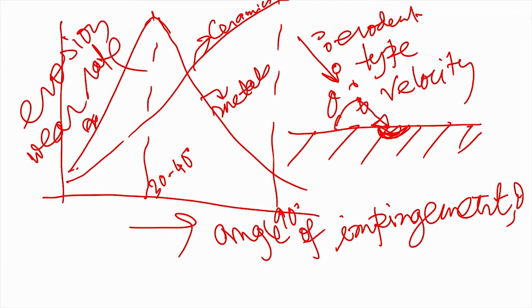So, the point that I am trying to make here is that when you do erosion wear experiments with metals, you should conduct these experiments preferably at 30 to 40 degree, because at 30 to 40 degree the erosion wear goes through a maximum. When you develop new materials for wear resistance applications, it is important and imperative to understand their wear mechanism and also measure their wear loss at the most aggressive wear conditions as much as possible. So, for ceramics, the angle of impingement should be 90 degree to assess the wear resistance under the most aggressive conditions, and that is an impingement angle of 30 to 40 degree for metals.